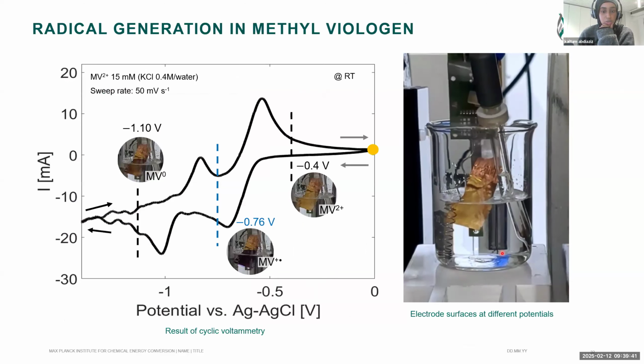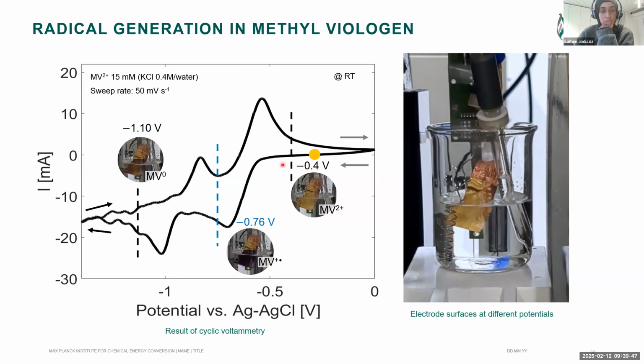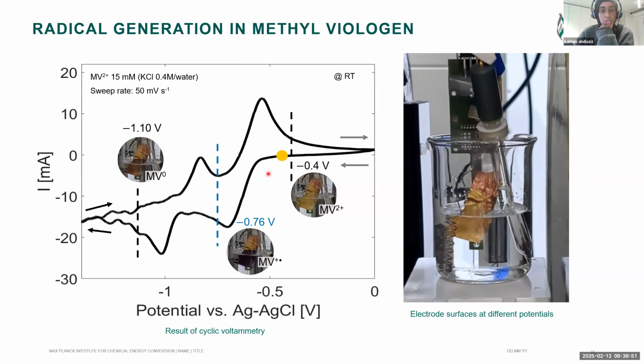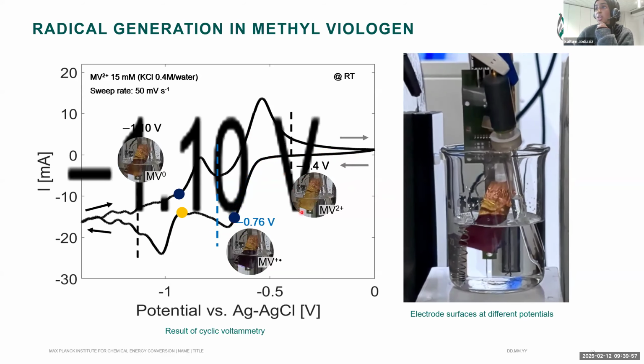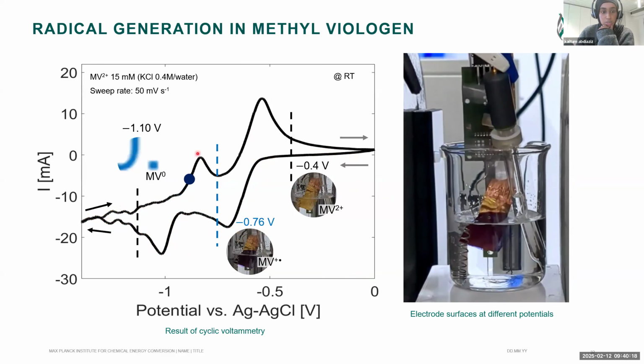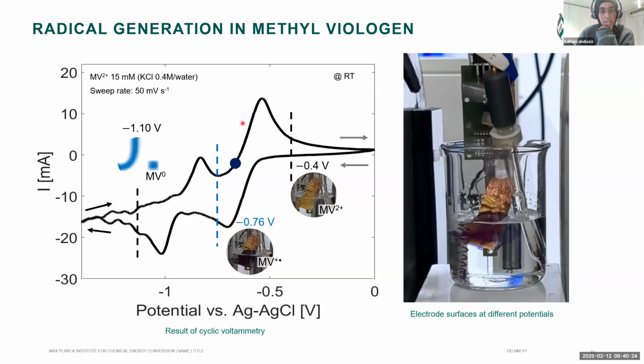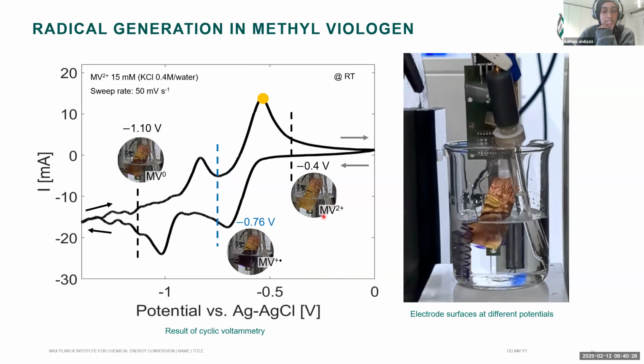So again, methyl viologen was used as a test subject, where he scanned, and you can see that the electrode starts to change color as you go towards the first reduction potential. And then the color starts to disappear as you're going towards the second reduction potential. And in the reverse, you should also see that the color intensity goes higher when you go towards the reduction potential of your methyl viologen radical, and then back to an EPR silent dication.